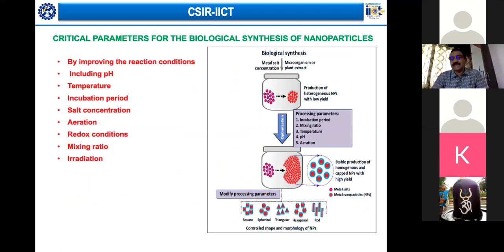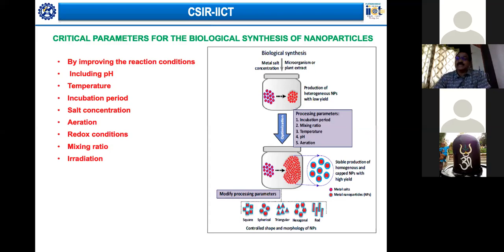So here again, there are some critical parameters which are also very important, and these are the ones which can be controlled to synthesize these materials. Like in biological synthesis, you have the metal salt, you have the microorganism or the plant extract, you take them together. And these are the parameters that need to be optimized: the incubation period, the ratio in which these two are mixed, the temperature at which the reaction is performed, because in my earlier slide I showed you that it is done at 90 degrees. Here you can play with the pH. With that also, you can end up with materials of different sizes and different shapes, and aeration or calcination, those are all the things that are also there. By playing with these parameters, you can synthesize these materials in different shapes, like square, spherical, triangular, hexagonal, rods, and so on. These are all colloidal shapes of these materials which are possible by these kinds of studies.